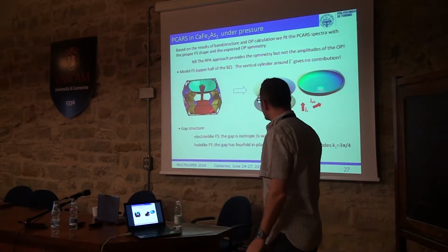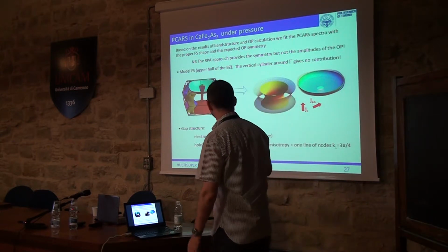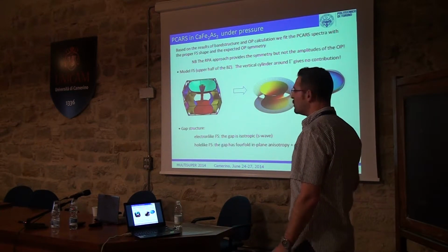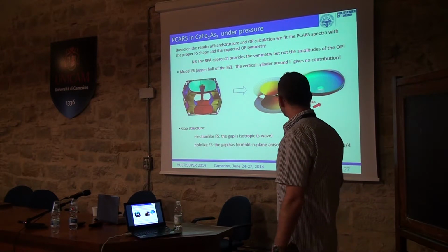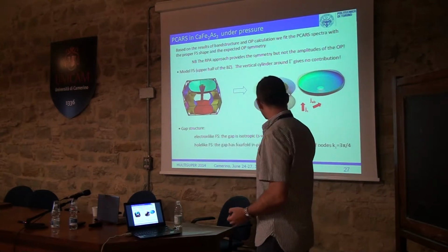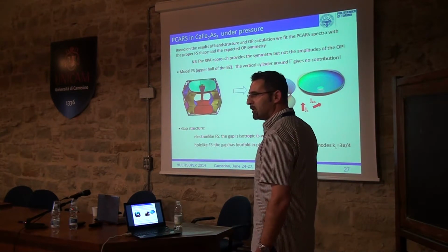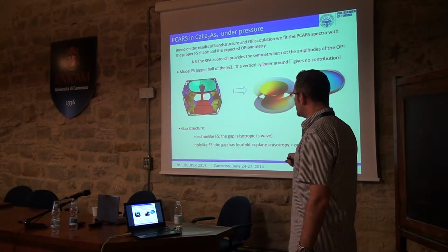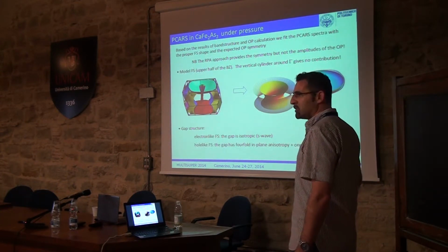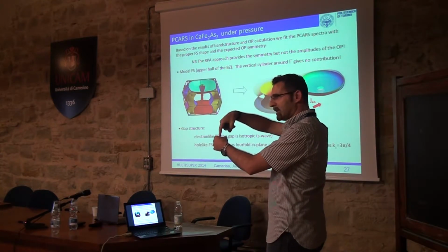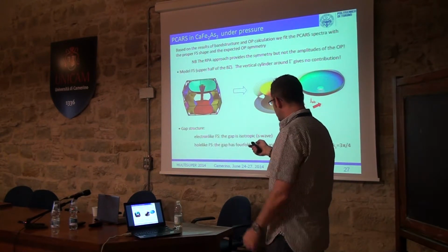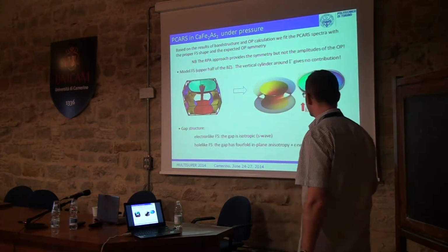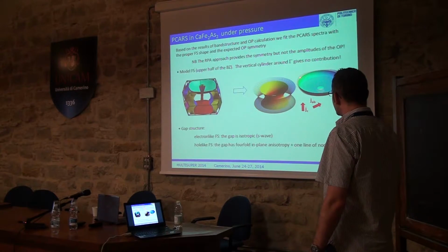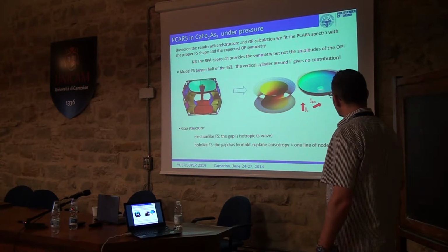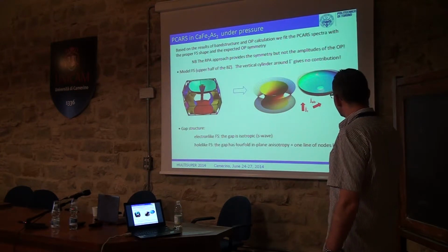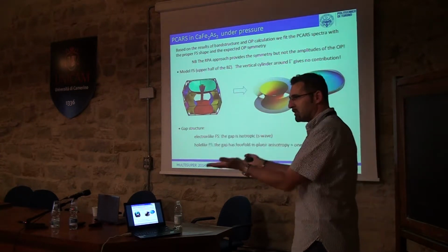So this is the Fermi surface. I did not show the gap because it is difficult to draw, but we mimicked this by using a model Fermi surface. It looks completely different, only because for clarity I changed the proportions, and this is only the top half of the Fermi surface. This small cylinder here is neglected because for C-axis injection it has absolutely no effect, no weight, and for A-axis injection it has a very small weight, a small surface. By the way, this gridded surface is the gap. You see that it has a fourfold oscillation, but it has no vertical nodes, and the nodes are like here where it crosses the Fermi surface.